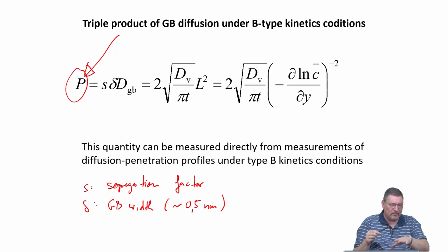I suspect, as I showed you for the pure copper, that small deviations in inclination, in misorientation of these boundaries serve to have different structural units with different distribution of excess volume, which means the local chemical potential for segregating species to go or not to go to these places will be different. And this is what we see in the end without having the detailed knowledge of the reasons, but it's, I think, a good concept to work with.